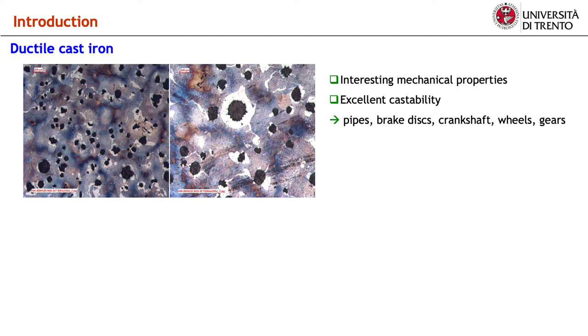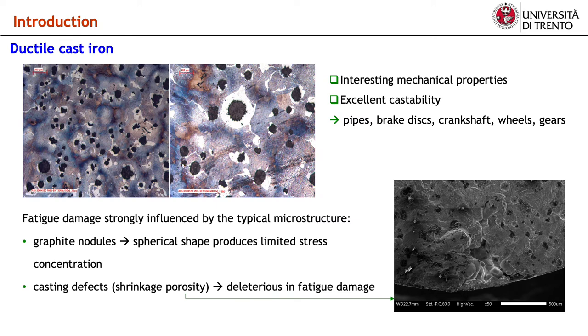This is in general employed in the production of large thick-walled castings. The resulting unfavorable solidification conditions lead usually to the formation of casting defects, such as degenerated graphite nodules and shrinkage microporosity, which impact detrimentally on the fatigue strength.